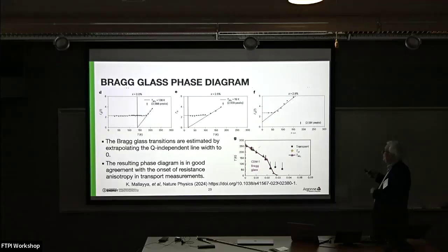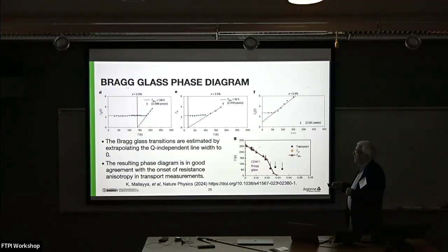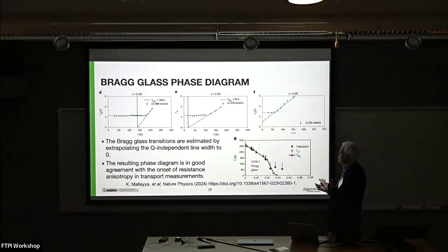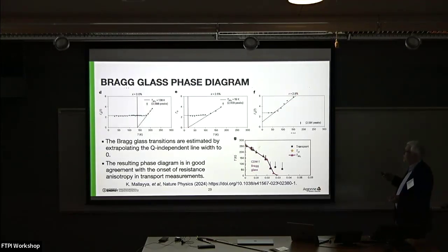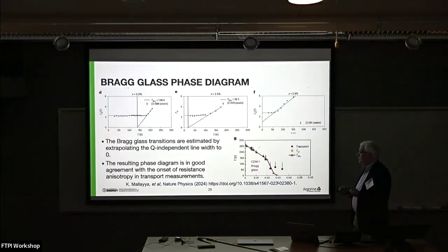We saw that in niobium selenide as well. I never understood it. Here, once you get below a resolution limit, then you won't see a change anymore. But if you extrapolate that down, you can get a very precise measure of where the phase component of the alignment goes to 0, where you expect the Bragg glass phase to be. And it turns out that if you put that on a phase diagram, it exactly corresponds to the temperatures at which there was a change in the anisotropy of the transport. So it's consistent with previous transport measurements, but provides a new insight into the prevalence of Bragg glass behavior.